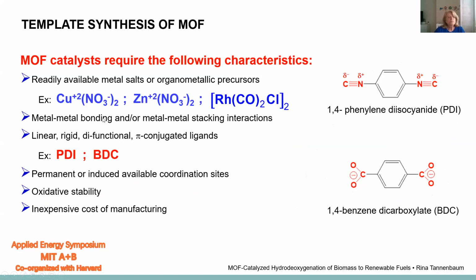And so we have looked at a variety of precursors to generate this kind of complex. And we looked at readily available metal salts or organometallic precursors such as copper nitrates, zinc nitrates, or rhodium carbonyl. And this is a transition metal. The nice thing about rhodium is that usually complexes of rhodium end up having a square planar geometry. And so we are going to require metal-metal bonding, and if not direct metal-metal bonding, then some sort of attraction between the metal centers to form metal-metal stacking interactions.